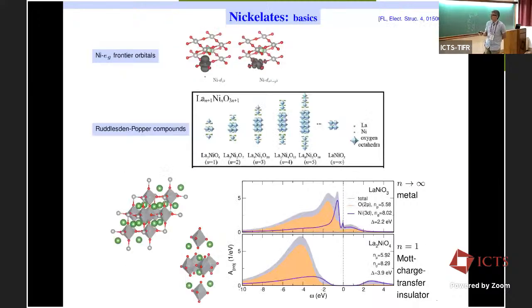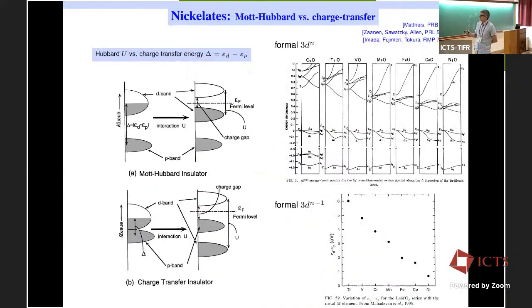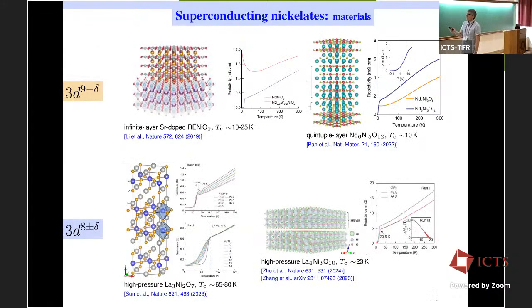And just going back to the values we had in the calculation, the charge transfer is small for lanthanum nickelate, so this corresponds to this plot of 3d7 that we have seen in other slides, so very small, whereas it's quite larger for the other system of 3d8 kind, which is the one above, and this would be the one below. So that matches more or less this scheme that we see in these trending pictures. So the charge transfer energy is still high in these nickelates generally of this Ruddlesden-Popper kind. So let's move on now to the concrete systems.